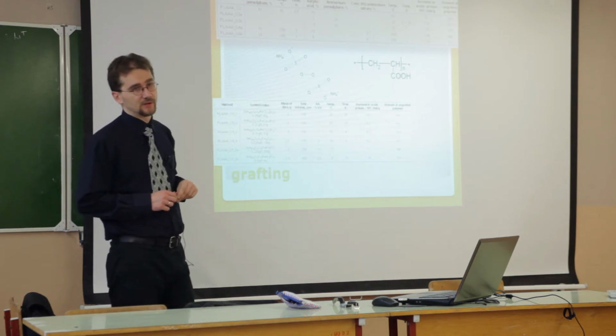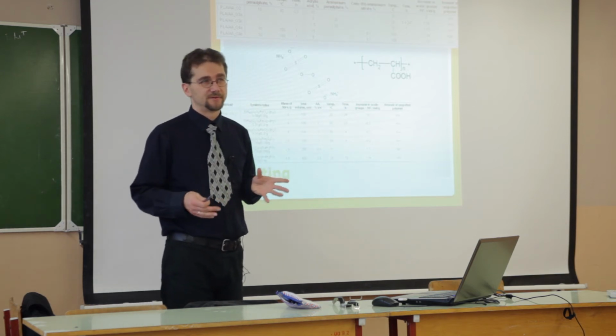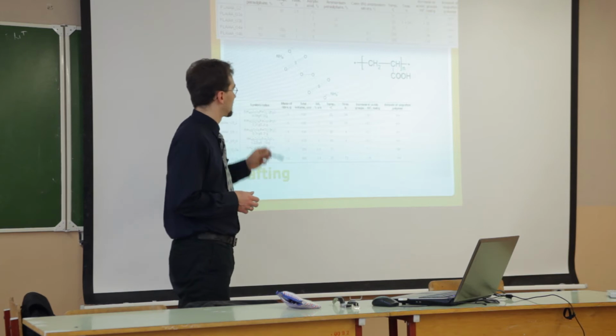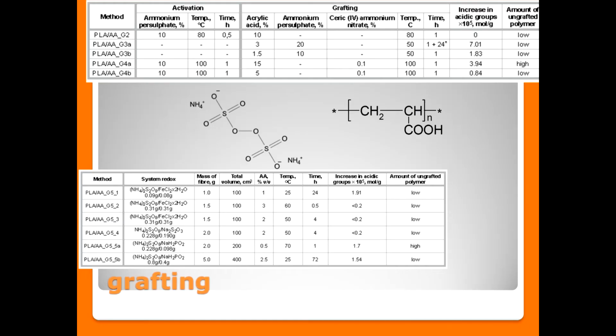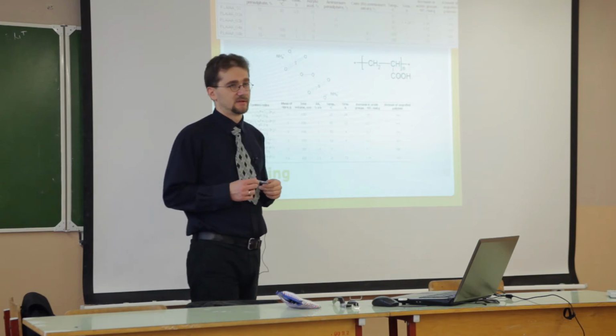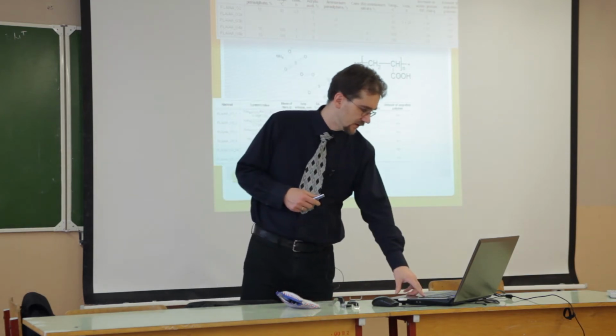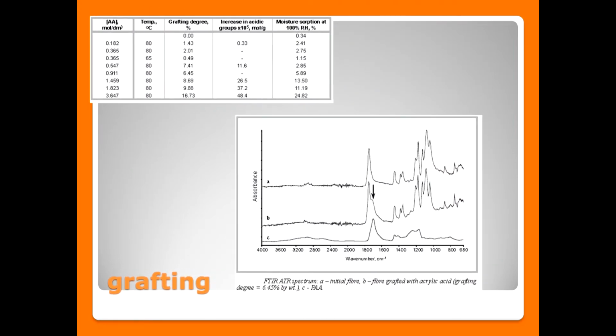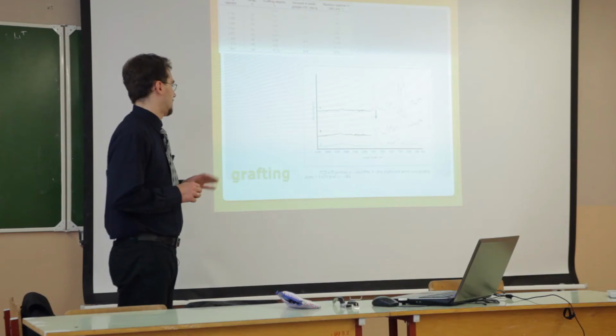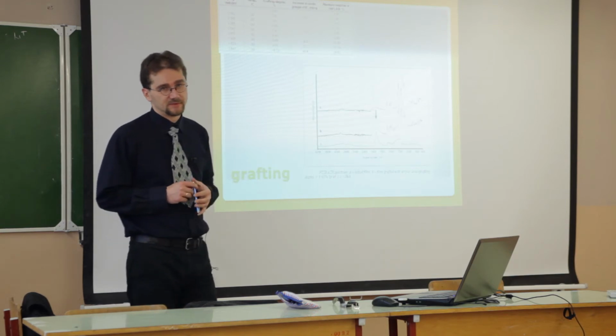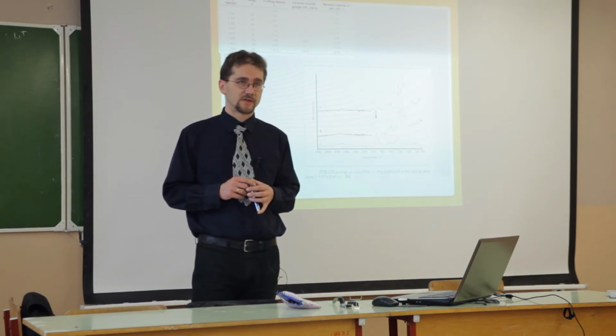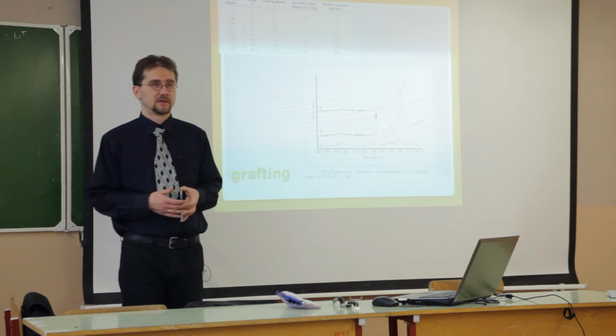We tested and controlled different times for using ammonium persulfate, different concentrations of ammonium persulfate, different temperatures, different processes and conditions, and different concentrations of acrylic acid. We found the most efficient way for production of grafted material, and it is important to find how we can control the structure, because making the modification is only one step.